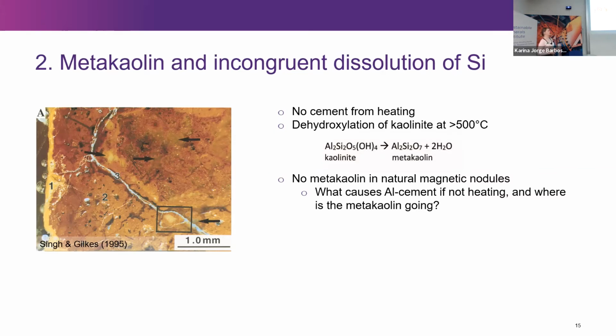The second big issue was that we know that there's dehydroxylation of kaolinite at 550 degrees. If I have kaolinite in my sample, I'll have metakaolin in the sample after I've heated it. But in the wild, magnetic nodules don't have metakaolin. And I could tell this from some thermogravimetric analysis I did. So if I know metakaolin should be forming, where on earth is it gone? And what's making the cement?